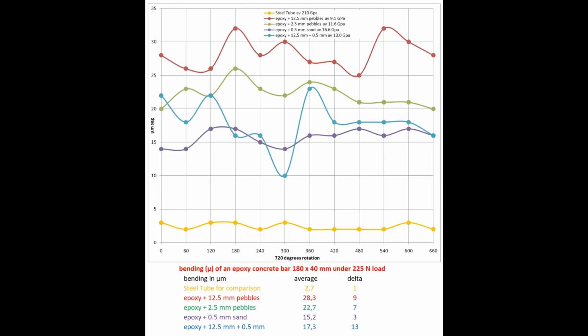All in all, I draw the following conclusions. If dimensional stability and strength are not of great importance, and costs must be kept as low as possible, choose a mixture of pebbles and sand. Only 18 volume% epoxy needs to be used for this. However, the high risk of trapping air bubbles must be taken into account. A vibrating table or vacuuming for a short time to allow the air bubbles to rise can also offer a solution.